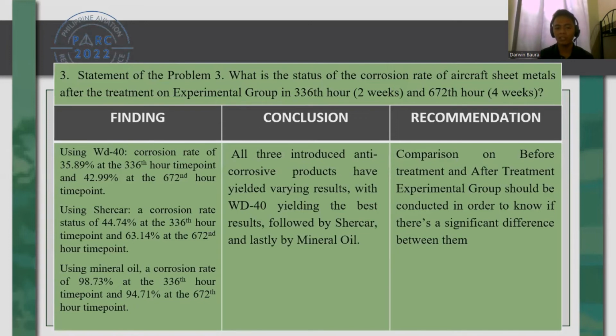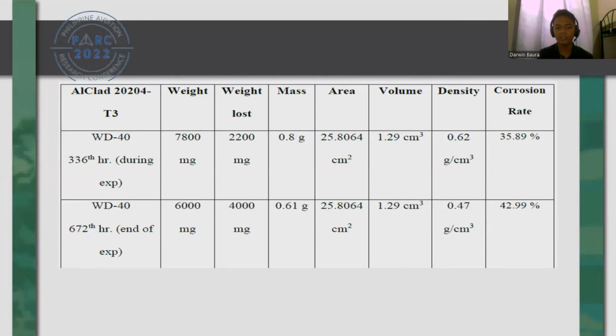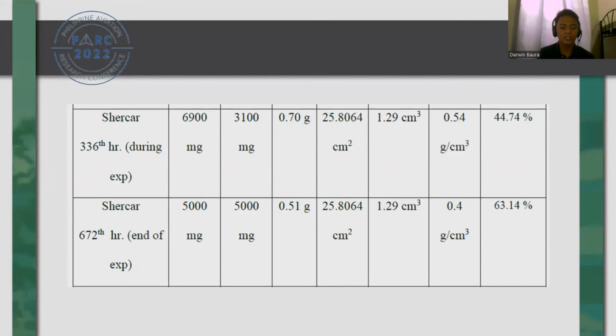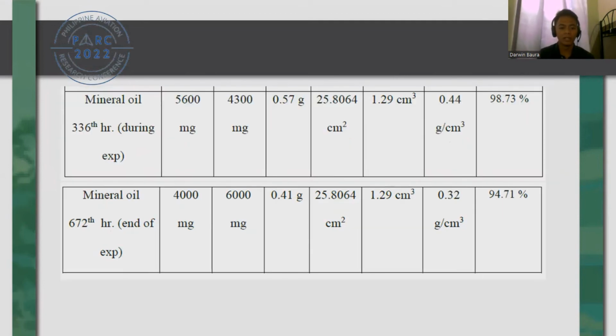Statement of the problem 3 will identify the status of corrosion rate on the after treatment experimental group. For WD-40, it has a corrosion rate of 35.89% at 336 hours and 42.99% at 672 hours. Both are significantly lower compared to the before treatment corrosion rates. Shercar at 336 and 672 hours is a little bit higher compared to WD-40, and the mineral oil at 336 and 672 hours has the highest corrosion rate of them all, which is closer to the before treatment corrosion rates. So the lower the corrosion rate, the more effective the product is. But the higher the corrosion rate, the less effective the product is.